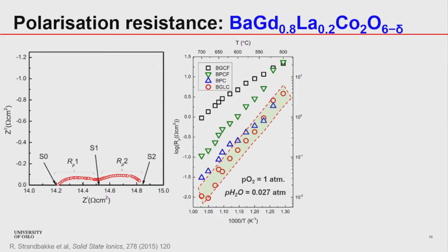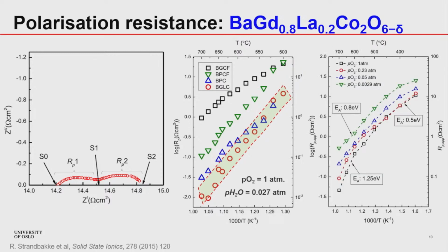Next, if we change the PO2, we can understand more about the system. What we see is that if we go from high PO2 to lower PO2s, the RP decreases. This is the usual behavior: you are decreasing the reactants, you are decreasing the oxide ions, so the RP is decreasing.